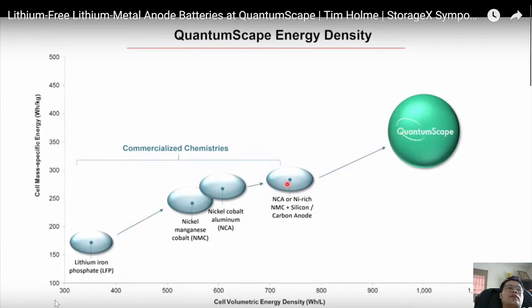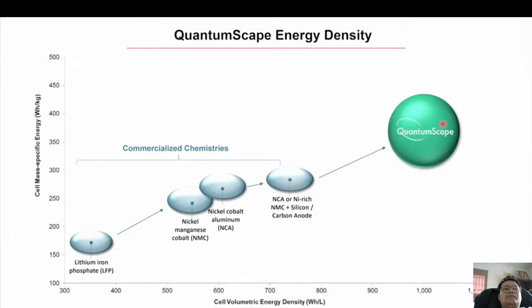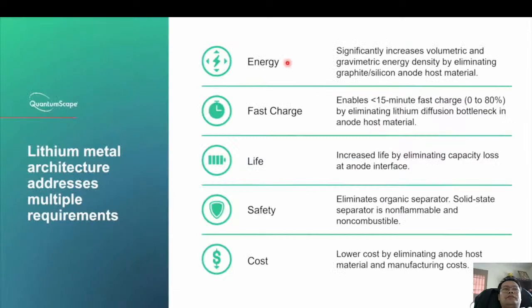Of single-digit percent per year improvements in energy density by switching to this lithium metal architecture. So that's the target. In terms of energy density, by removing the host material, we hope to improve on energy. By eliminating this lithium diffusion bottleneck that I talked about, we hope to enable fast charge. By eliminating this SEI formation and growth, we hope to improve in life. By eliminating a lot of the flammable materials in the cell, we hope to improve in safety.